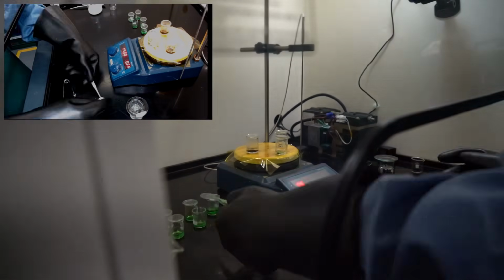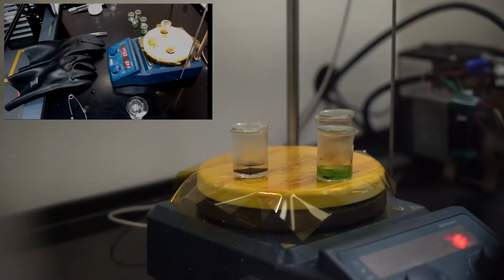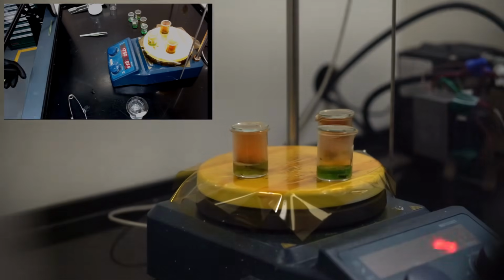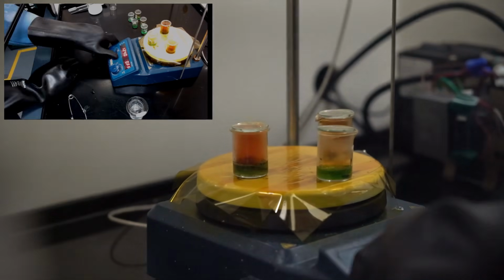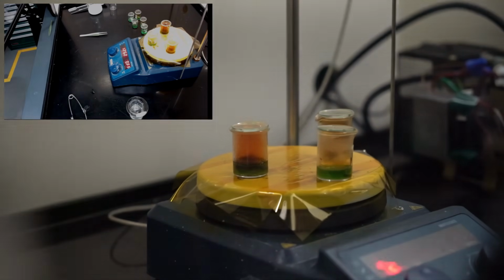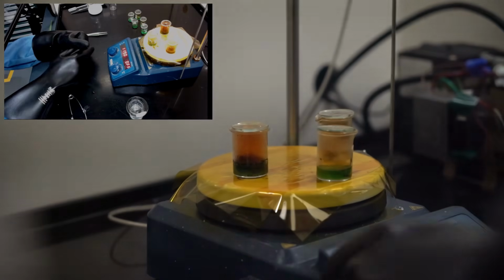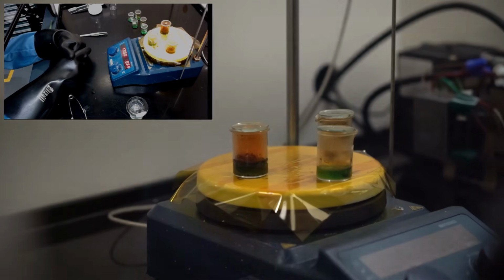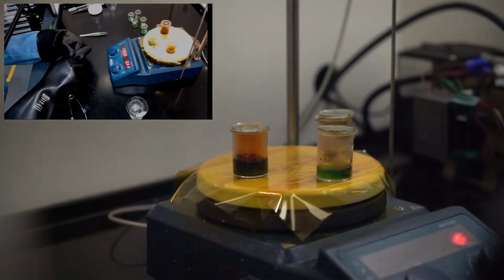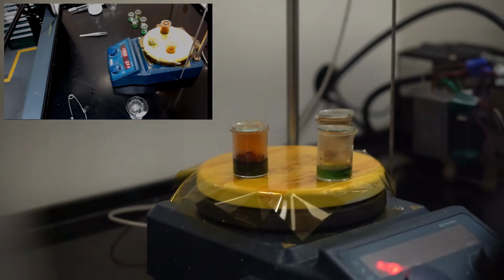I put a few of the samples off to the side because I can't fit them all on the hot plate at once. Also, if you'll notice, the acid was turning green already, and sometimes if you've got a big thermal pad, the sample will start to react a little too aggressively. To keep from boiling over, I'll let it sit at room temperature and eat through a bit of the copper before I start heating.